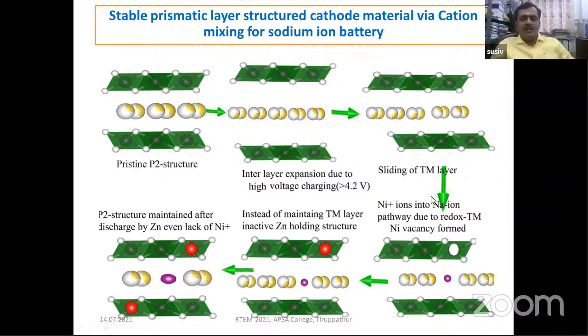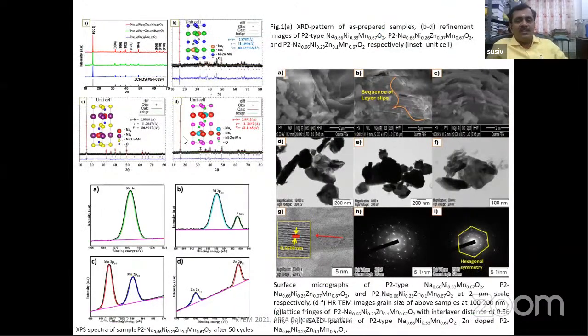Then suddenly it creates the vacancy, Ni vacancy. That Ni vacancy has been equalized or neutralized by adding electrochemically inactive Zn into it. It holds the structure. So that has been proven by our experiment, to maintain a very good cycle life and good electrochemical properties and performance. See, these are all the results, and here also you can see the stack-like arrangement, sequential